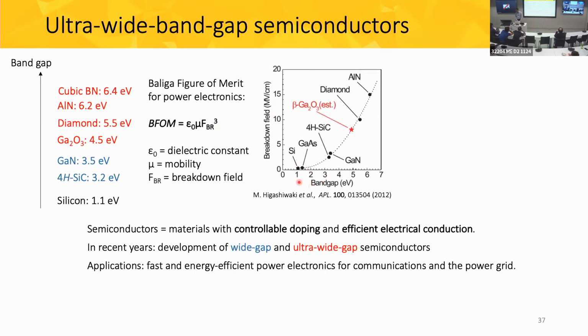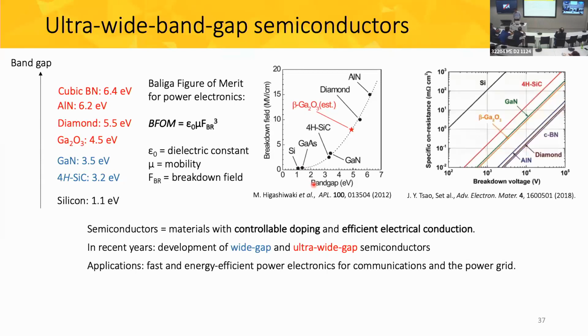So you see that when you employ materials with wider bandgaps, the improvement in efficiency is superlinear, the 6th power or 9th power with respect to the bandgap. And so if you look at the benefits of these wide bandgap materials, you see them in this plot.